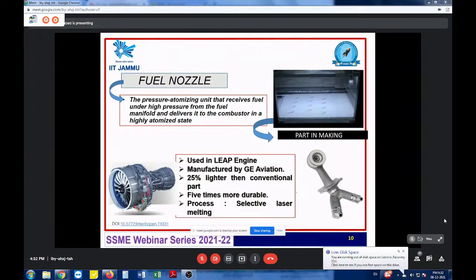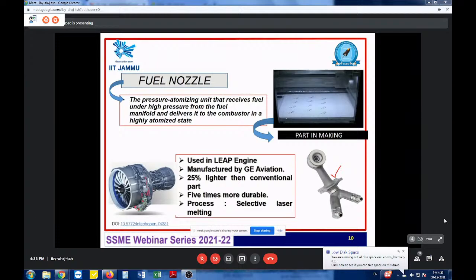Another aerospace application device is a fuel nozzle developed by GE Aviation using a laser-based SLM process. The fuel nozzle is used in a pressure atomizing unit that receives fuel under high pressure. The component is continuously subjected to high pressure, so surface finish must be at an optimized micron level to avoid becoming a crack-initiation site. If the component cannot adapt to the high-pressure environment, it will give up, leading to catastrophic failure.